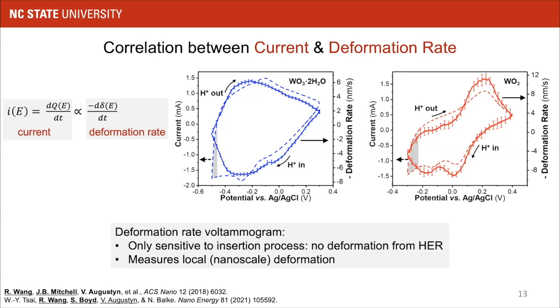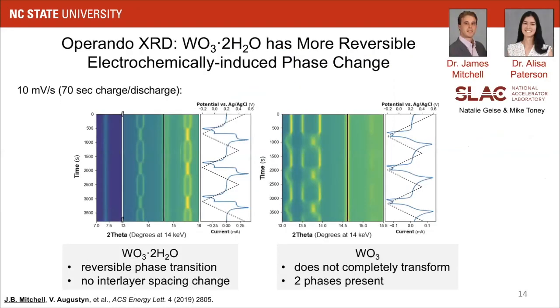For our purposes here, though, it showcased that there was another aspect that we could consider for why the hydrous material showed more reversible proton insertion, and it had to do with this structural response. Using operando X-ray diffraction, we were able to further correlate this response to a more reversible electrochemically induced phase change. This is operando X-ray diffraction performed at SLAC by James Mitchell and Alisa Paterson in collaboration with Mike Toney's group. And what we observed at different scan rates is that the tungsten oxide hydrate always showed this very reversible phase transition with proton insertion.